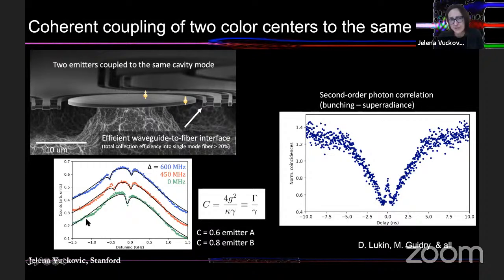What you see on the left is, as we're changing the tuning between these two color centers and the cavity resonance, these dips in transmission, known as dipole-induced transparencies, are changing positions. And when they're on resonance with each other, you see a single dip in transmission. So we are not in a large cooperativity regime, but we're starting to see signatures of the collective interaction and super radiance. These are extracted cooperativities for the two emitters.